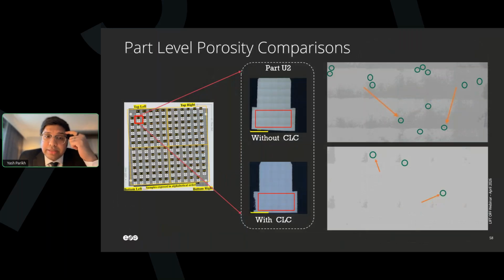You see the comparison here for that U2 part between without closed loop and with closed loop. So now you see the amount of reduction in these porosities, as-built porosities. Go to the next one. These are not bad porosity, they are not connected or linear, so it can be easily fillable with the hipping process. Go to the next one.